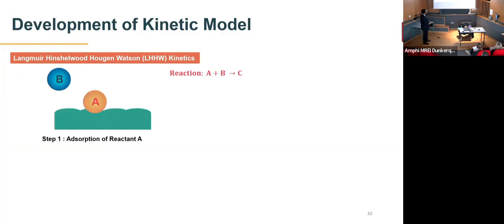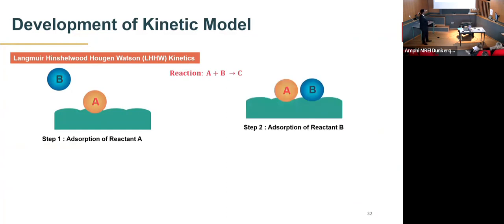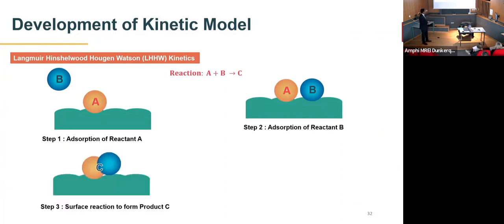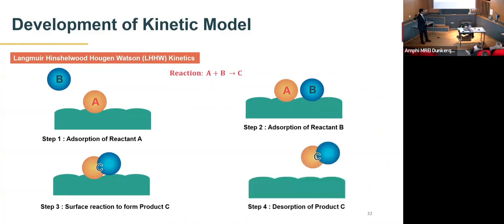So in the first step, we have the adsorption of the reactant molecule A on the surface of our catalyst. In the second step, the second reactant molecule B also adsorbs on the surface of the catalyst. In step 3, there is an interaction between the A and B molecules that are in the adsorbed state to form the product molecule C, which is also in the adsorbed state.